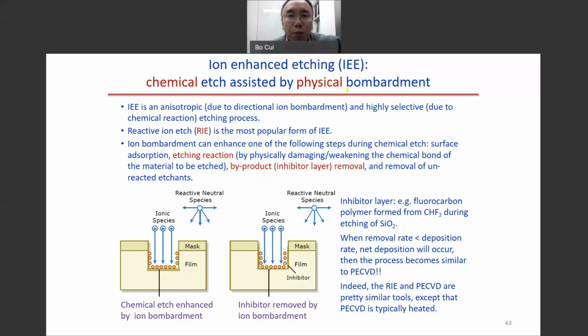So how will the ion help the chemical etching? There can be a few things that happen. First, the ion can help surface adsorption and help an etching reaction by physically damaging the chemical bonds of the material. For example, if this is silicon and we have ion bombardment, the bottom part will be damaged. The lattice will be damaged. When it is damaged, the etching will be faster. It can also help to remove the byproduct.